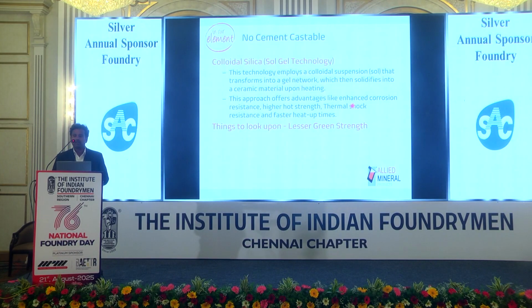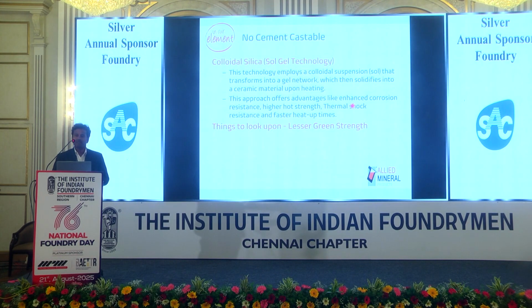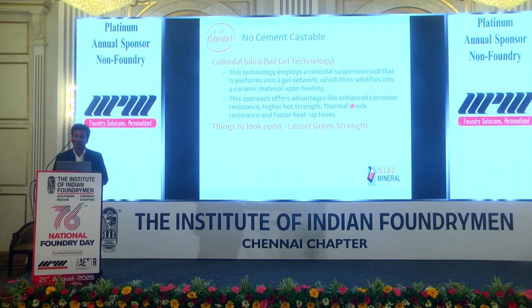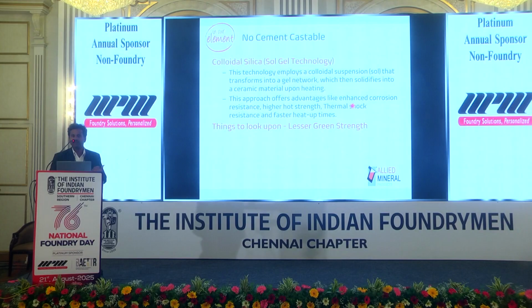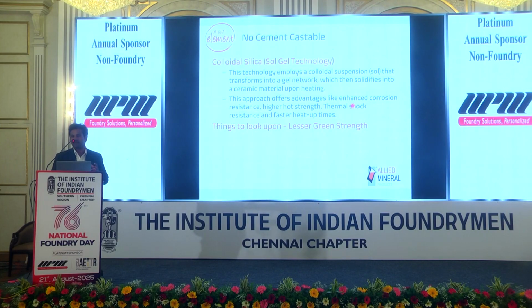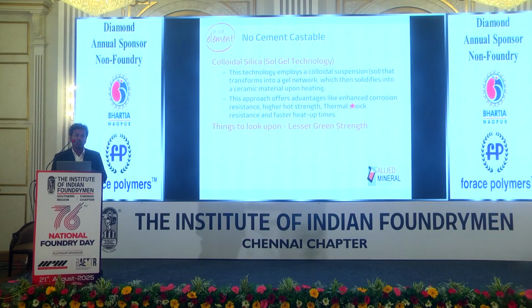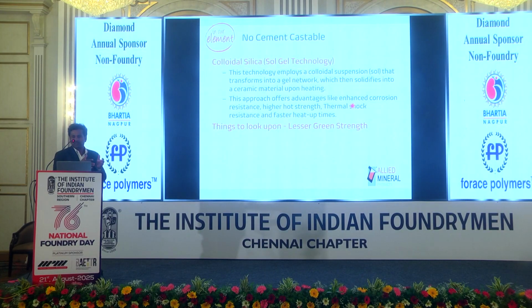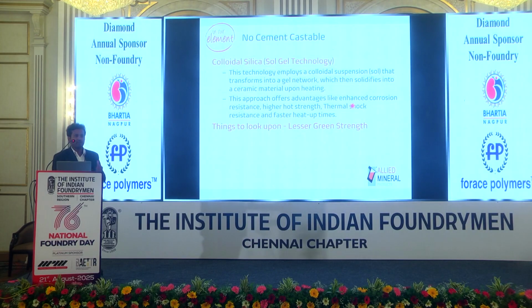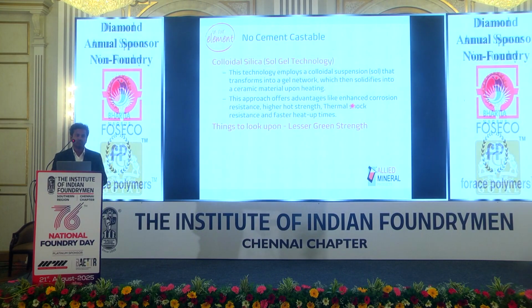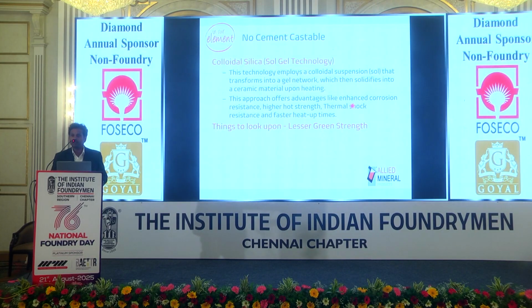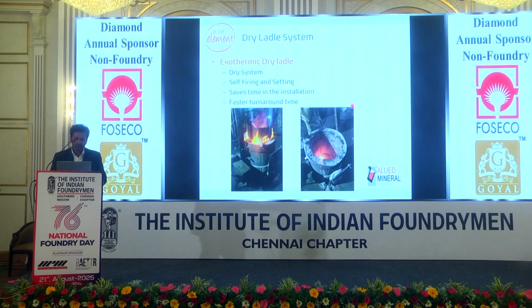This has a drastic advantage compared to a traditional cement-based system. It has very high hot strength and very high thermal shock resistance compared to the cement-based system. The only thing we have to be very careful about with the colloidal silica-based system is that it has very little green strength. When you cast the ladle, you are not allowed to mechanically impact the castable because it has very little strength. Once it is heated, it has enormous strength. That is one particular point we have to remember when using a colloidal silica-based system.